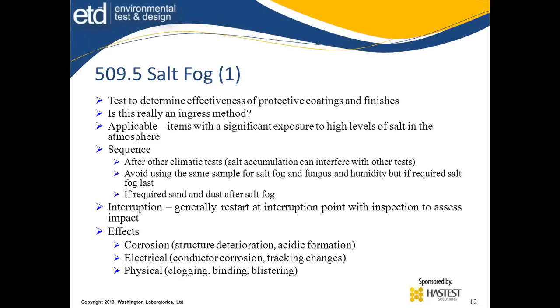The physical effects associated with it, the clogging, the binding, the blistering effects of the salt. And watch for connectors, things that we see externally getting into the connectors. Well, it was there. It's obvious it's going to get into there, and you didn't have a connector cover or a mating connector on it to protect it. Does this allow the salt to creep through the metalwork and cause corrosion inside the test article? We've seen this occur at random where a hermetically sealed connector, the salting environment tends to bind through. So one of the inspection criteria is a thorough inspection inside.